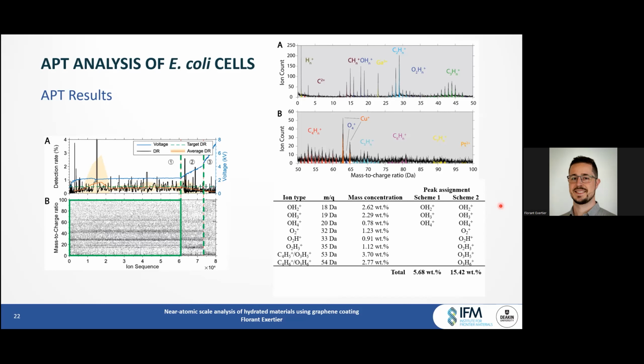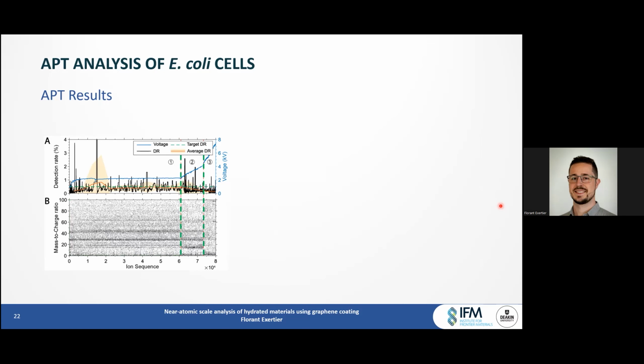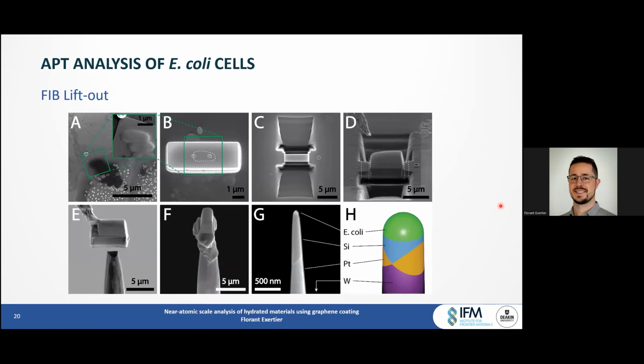So when it comes to graphene coating, I analyzed a lot of samples, and the fact that I never got any peaks higher than 45, as was mentioned in the water study, indicates to me that at least it doesn't come from the graphene coating. And as far as impurities go, as I showed here, I tried to target the E. coli cells with as much precision as possible, using the platinum button deposition that was described in another work, and we really did our best to target the cells with the utmost precision.